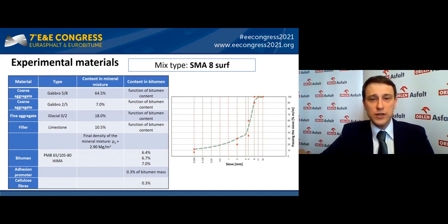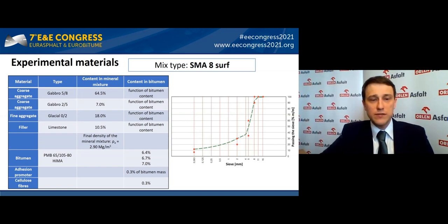The second part examines the impact of overheating in comparison with compaction at recommended temperature. In both methods — C index and void content after 50 gyrations — below 145 degrees Celsius, deterioration of compaction effectiveness can be shown when the mixture and bitumen are overheated. Therefore the conclusion and recommendation is not to produce and condition mixtures with PMB HIMA bitumens above 175 degrees Celsius, as it can lead to workability deterioration, which can be shown on site and make works difficult.